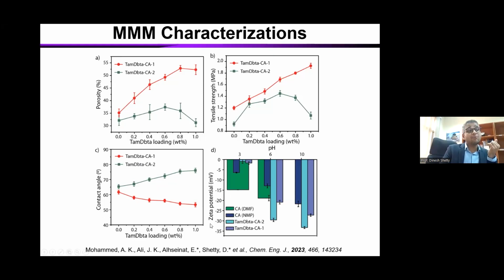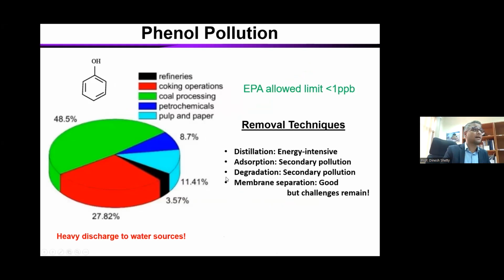Then we tried to understand the surface charge of this, the zeta potential. When we introduce these COFs into the system, we increase the negative potential, which means negative charge of the surface, because we have free OH in the COF as well. So we have a mechanically stable membrane now. So what can we do? We tried using this for phenol removal from polluted water.